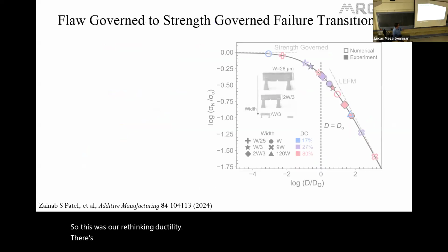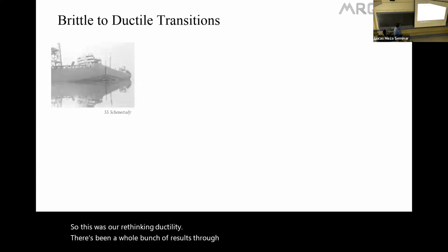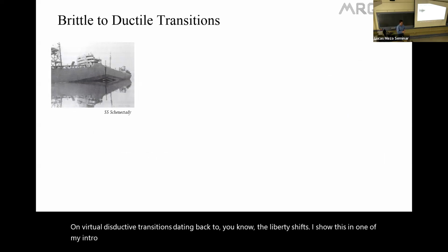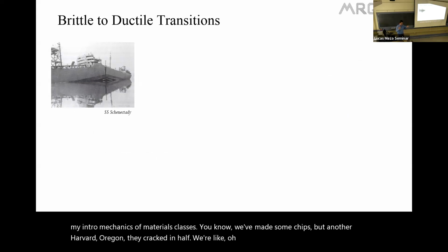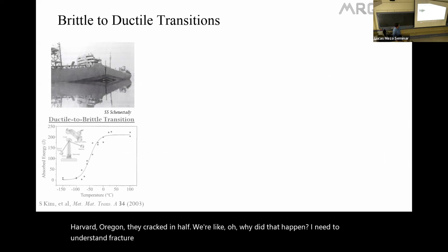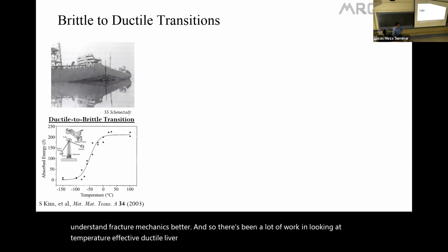There's been a whole bunch of results through history on brittle to ductile transitions, dating back to the Liberty ships. I show this in one of my intro mechanics of materials classes. We made some ships, put them in a harbor in Oregon, they cracked in half, and we're like, oh, why? Why did that happen? I need to understand fracture mechanics better. And so there's been a lot of work in looking at temperature affected ductile to brittle transitions, microstructure affected, size affected. All of them look at, I take a sample and I break it and I have some energy dissipated based on these temperature affected changes.